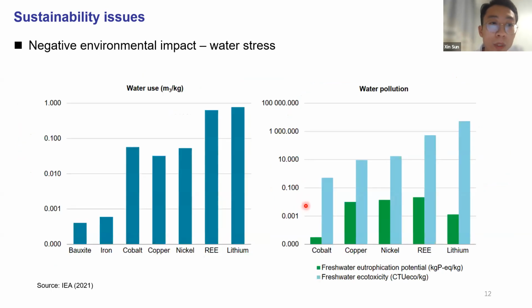And another negative environmental impact from critical material mining is water use. For lithium and the rare earth metals, which are also used in the electric vehicle and wind power because they are essential metals for the electric motor, the water use intensity is much higher than the other materials. You can see that the water use intensity for lithium and rare earth is 1 cubic meter per kilogram, but for others it's 0.1. It means that they are 10 times larger than the other materials. And for water pollution, it is also about 10 times or even 100 times higher for lithium mining than for the mining of the other materials.